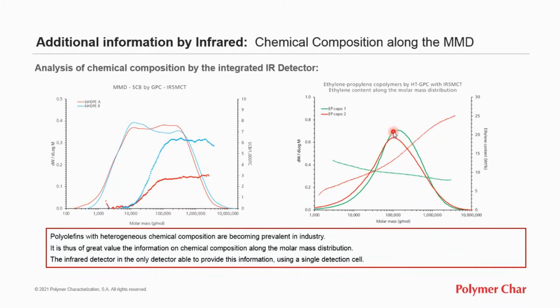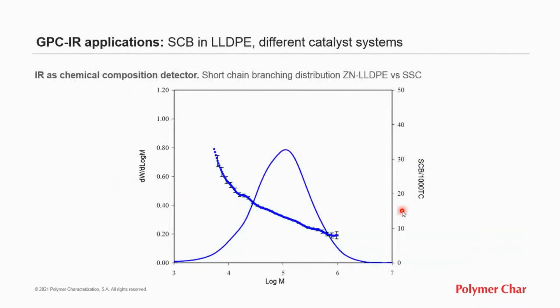Another interesting application we see on the right-hand side: two ethylene propylene copolymers, which have similar molar mass distributions, but the ethylene fraction distribution along the molar mass is quite different. One of them, the one in green color, is quite uniform. This is the ethylene content around 10%, as measured by the infrared, while the other, in red color, is more heterogeneous and has a larger content of ethylene in the high molar mass fraction. The IR detector is the only detector that can give this information coupled with GPC.